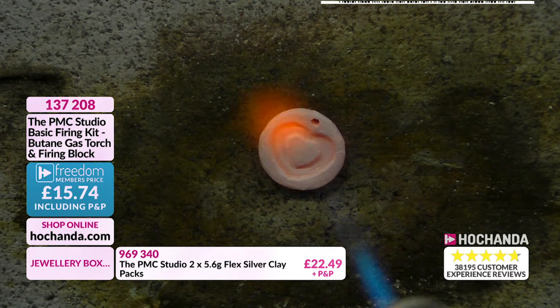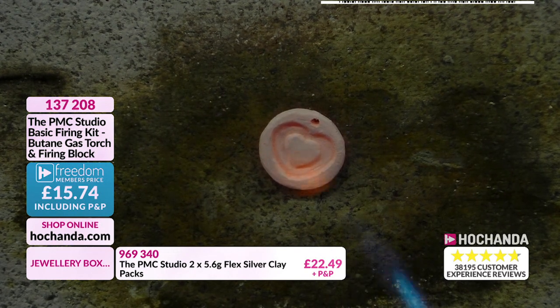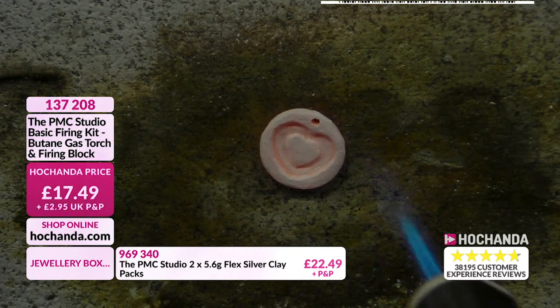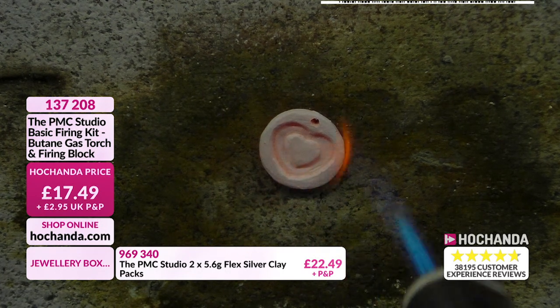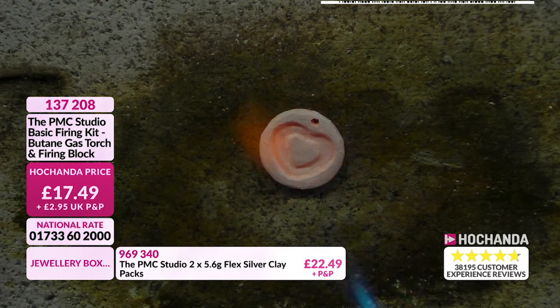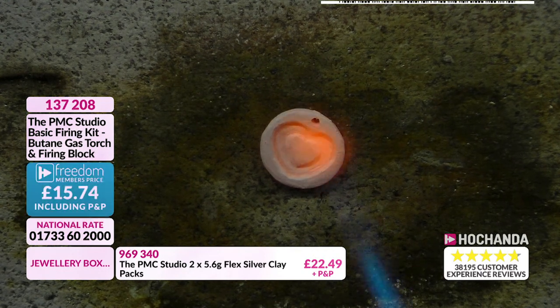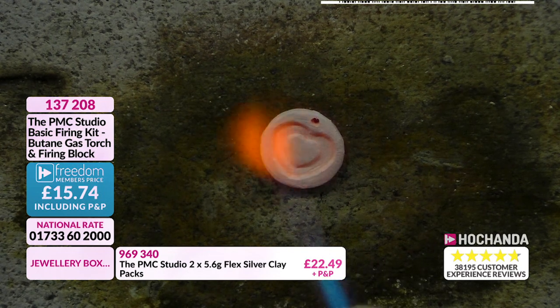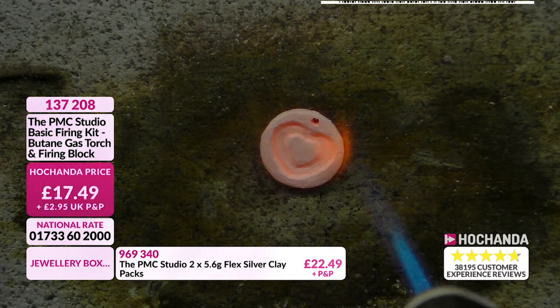Do you want me to time 2 minutes? Yeah, you can do 2 minutes. You can do longer. You can do 2 days if you really want to. You can fire as many times as you want, as long as you want. The minimum is 2 minutes. If you go any higher, then you start to melt it. Then you've melted it. So don't let it get to red. You're going for that pale orange glow that you can see here.